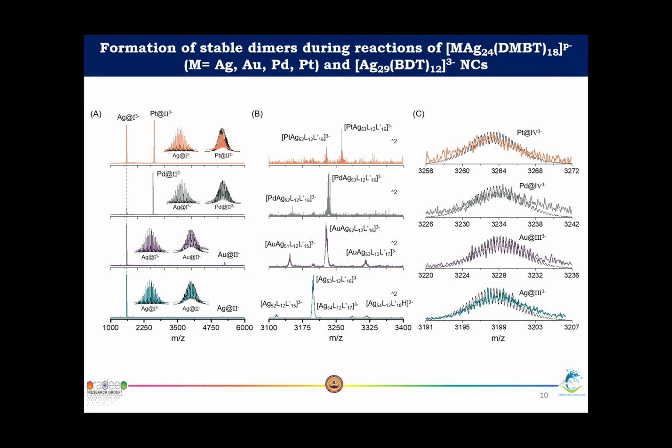But with all of these, there is the thought that was said previously that you need to do this measurement. Vivek was saying it takes time. So a technique which is short enough is important. X-ray scattering is such a short technique. The scattering event has to be short, like the mass spec event is short, whereas the UV-visible spectroscopy event is long, NMR is long. So you need sufficiently short events to do this. There is a possible range of techniques that one can have. We have not really looked at this domain.